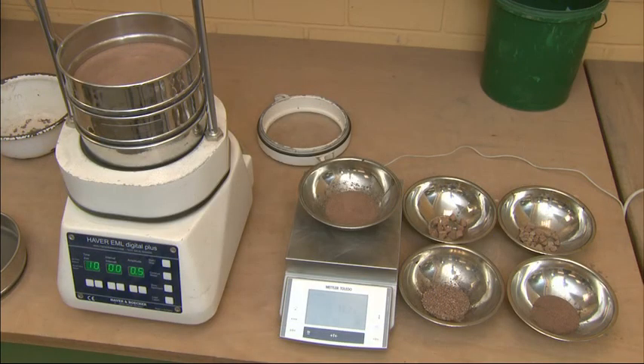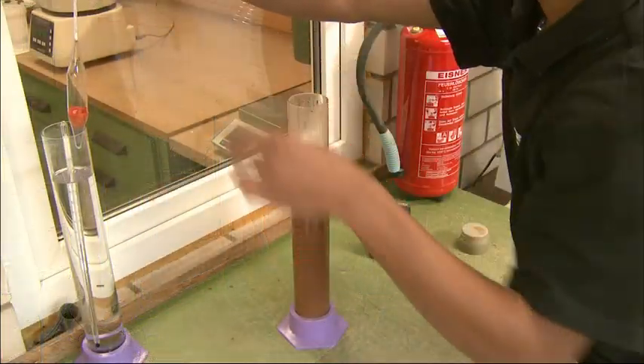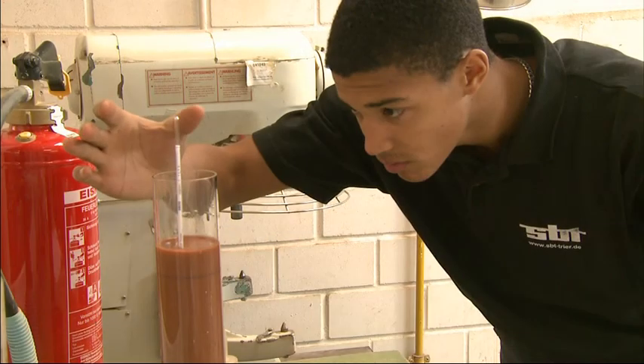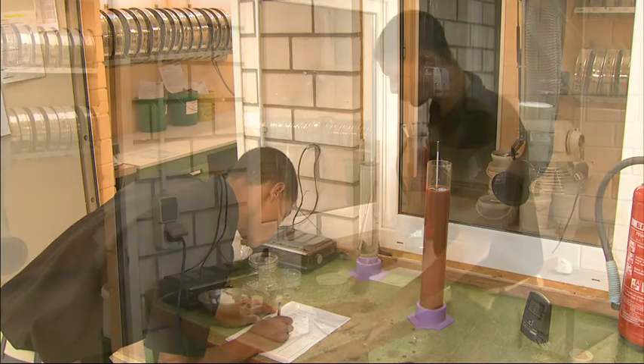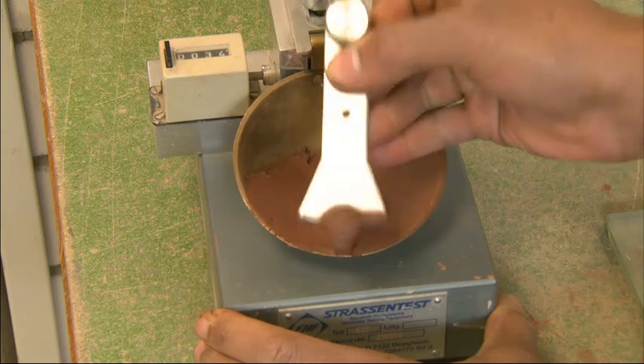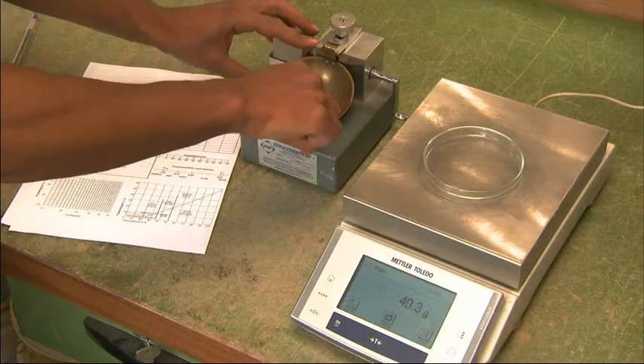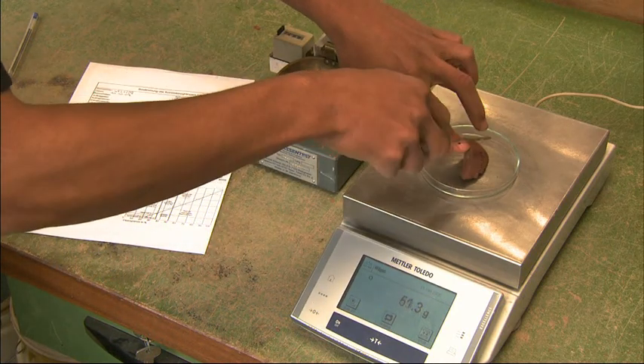Soil samples taken in situ are subjected to various different tests in the road laboratory. With a combination of sieve and sedimentation analysis, the grain fractions are separated so that grain size distribution can be established. A further test for material identification is the liquid limit and plastic limit test. This enables portrayal of the plastic properties of the soil. The grain size distribution and the established plasticity and consistency indices enable the soil type to be determined by means of a table comparison.